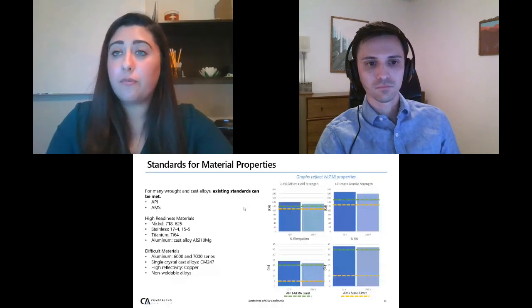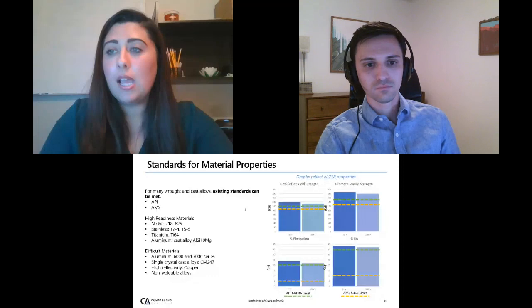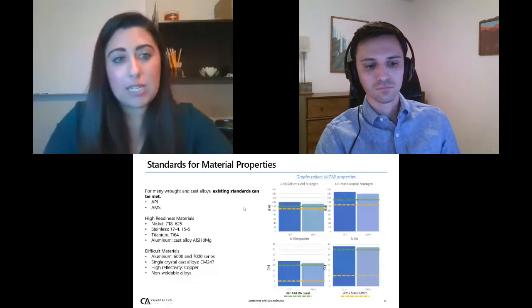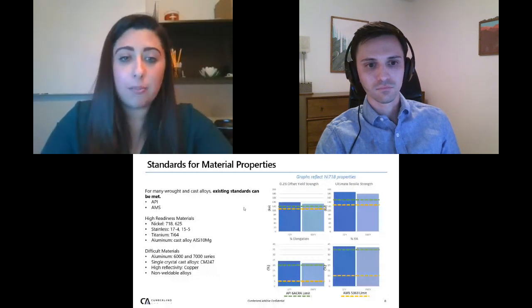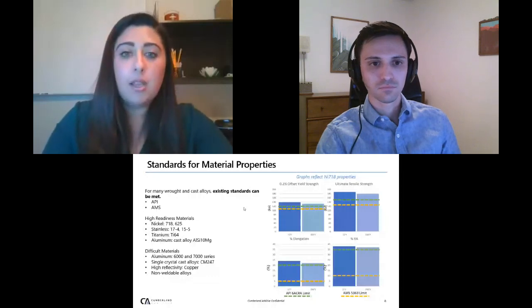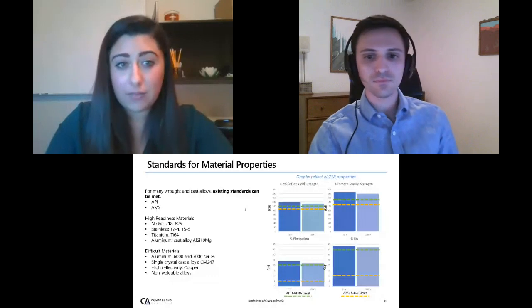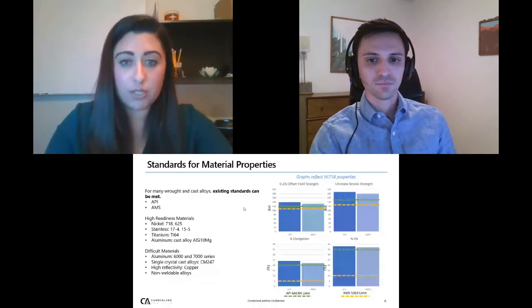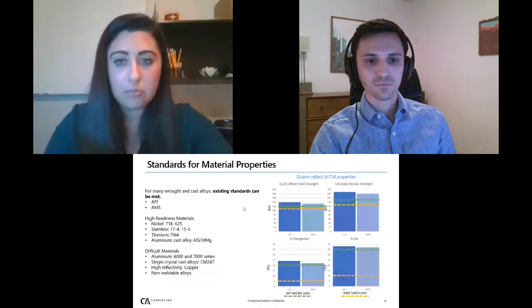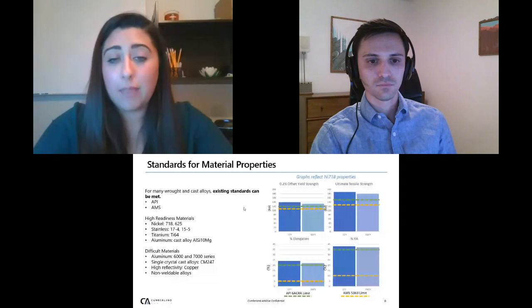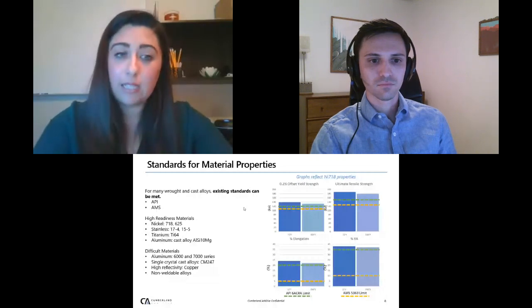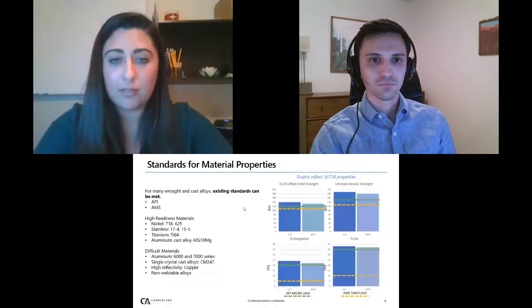So when we're talking about switching from traditional to AM manufacturing, we sort materials into high readiness and more difficult. Your high readiness alloys are going to be the ones that AM is already good at. They're ones that have a defined process, machine manufacturers are familiar with, materials readily available, stuff that has a low barrier to entry if you want to start printing this material. And then obviously there's some materials that don't really transfer that easily to AM. These are your more difficult materials, something like your 6000 and 7000 series aluminums. They might be a commodity in machining, but they are prone to cracking with laser powder bed fusion. So it's going to take a little bit of work from our dear metallurgists to make that more readily printable.